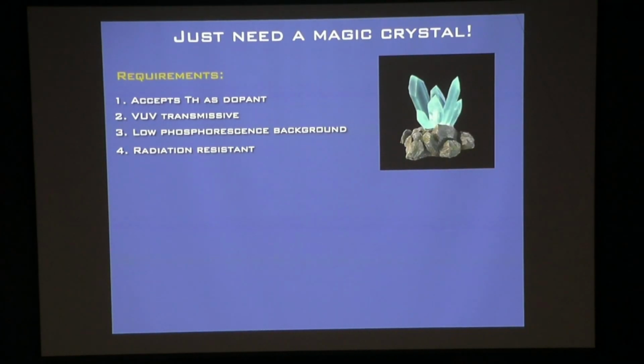16 years, I guess, was that you need a lot of things that just didn't exist at the time. You need this crystal that would accept thorium as a dopant. Thorium's a big atom. Most things don't want it. It needs to be VUV transmissive, so it needs a really high band gap. You want it to be radiation resistant because thorium-229 has about an 8,000-year half-life. This is like fairly radioactive, and so you don't want this thing to be damaged by the thorium.